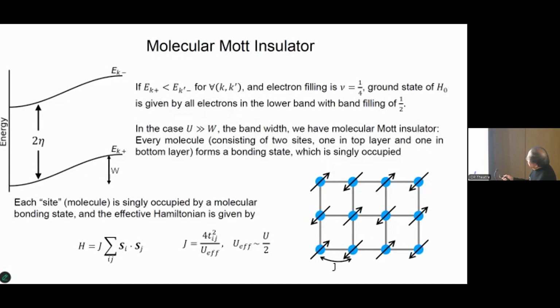So if I have U also large, then we have the so-called molecular Mott insulator. Every molecule, which I define to be just the two sites, one on the top and one on the bottom layer, will form a bonding state, and this is singly occupied. So the bonding state will be singly occupied, and that is described by the spin-1/2 Heisenberg model. We call this the molecular Mott insulator. Note that usually in a Mott insulator I have one electron per site. Here I have one molecule per site. Each site here represents one molecule, that means the top and the bottom sites.